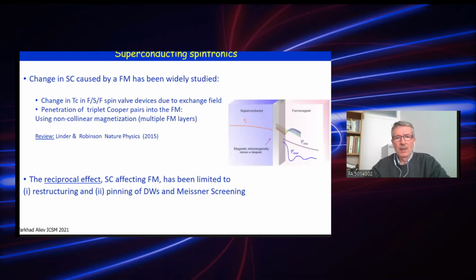So far, mostly the systems which have been studied are ones where we create a kind of spin valve and change the exchange field to change the critical temperature, for example, or also study the penetration of triplet Cooper pairs into a ferromagnet with non-collinear magnetization.